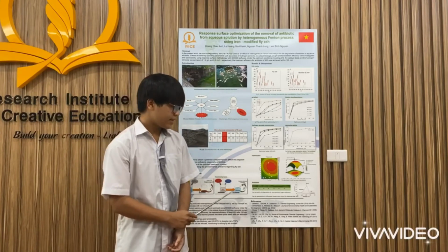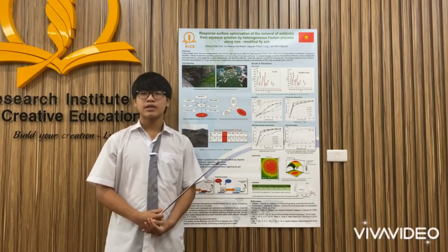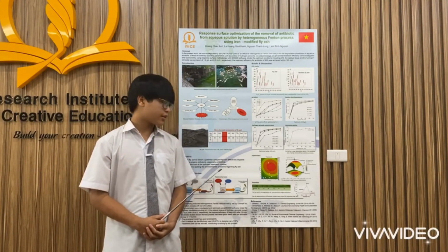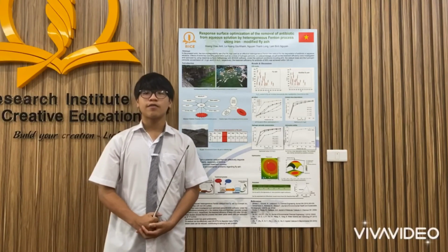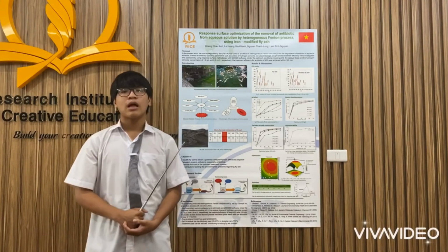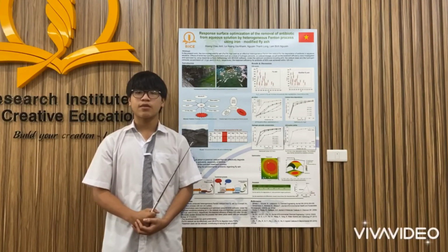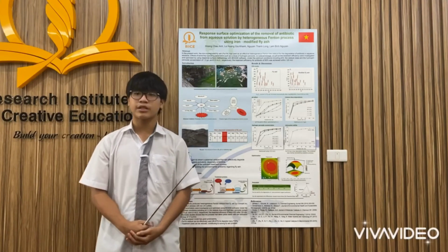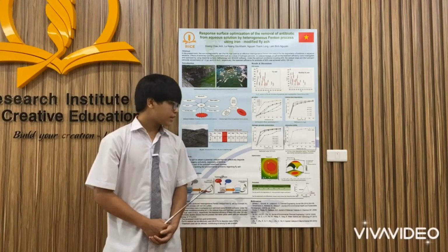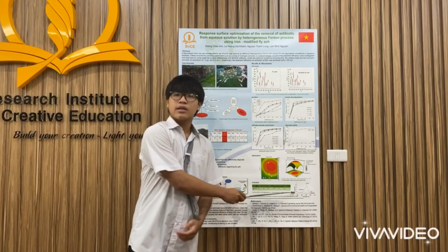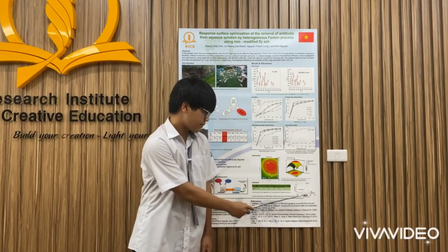The stability and recyclability of the iron modified fly ash catalyst was evaluated by recycling and reusing the catalyst over 5 consecutive cycles. After each run, the catalyst was separated from the solution by filtration and then dried for the next degradation experiment. The experimental results indicate that the catalyst can be separated and reused many times.